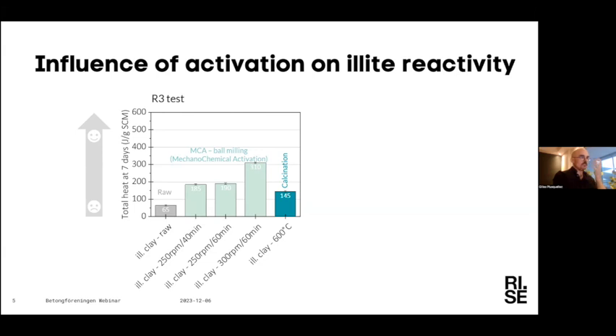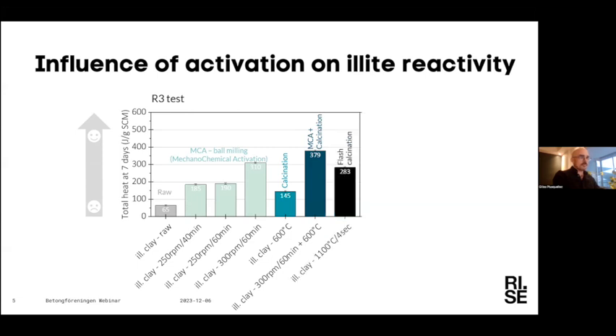For a normal calcination, as expected, the result is not that great. We also tried to combine those two methods, and there we have an even higher reactivity, which is pretty high for illitic clay. We tried also flash calcination. We are still working on the parameters here, so it's not optimal, let's say. But the idea was to give enough energy to the system to have this phase transformation, without the formation of the unreactive phases that I mentioned before. For flash calcination, you go to a really high temperature very quickly, you stay there for a few seconds, and then it's cooled down again very quickly. So we hope that we don't give time for those unreactive phases to form. And it looks like